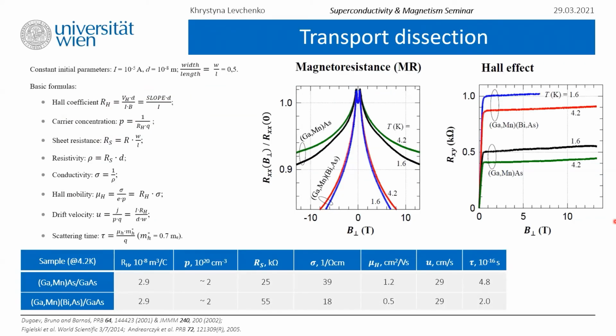And if you were wondering whether the bismuth is actually changing any basic transport parameters like carrier concentration, then the answer is no. It decreases mobility, but on a tolerable level. All this was found out by performing a set of transport measurements, again, this time in higher fields. So remember, this was the anomalous Hall effect that we discussed earlier and that we were investigating in the previous slide. And this is the classical Hall effect from which the carrier type, p-type, holes, and carrier concentration were determined. The measurements were conducted at 2 temperatures, 1.6 and 4.2 kelvin.